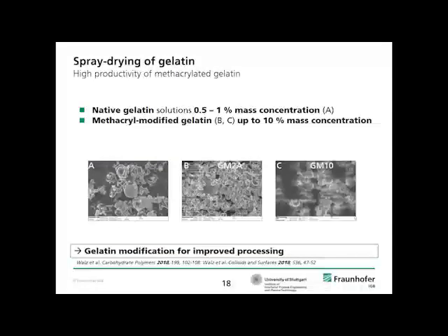Last but not least, we have the possibility to spray dry gelatin solutions. Just to give you an idea, native gelatin solutions tend to gel, and therefore you can only use very low concentrations of gelatin in this spray drying process. If you use modified gelatins with reduced gelation, you can really increase the mass concentration in the process, and you will be able to produce small particles, load them with active ingredients, etc.